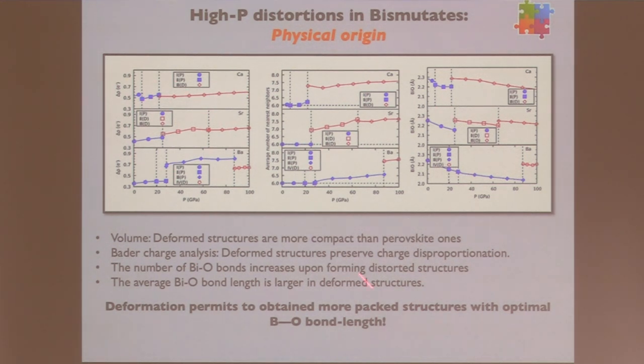What you find if you compute, same story, like bismuth 3 plus, bismuth 5 plus. Yes, if you compute in different DFT, you get a different distribution. But this tendency is so robust that you prefer to break the structure than to suppress this charge order. It's kind of an equal mixture of 3 plus and 5 plus. Crudely, they are alternating, but they are not alternating on a regular lattice anymore. That's what we think this thing comes from.